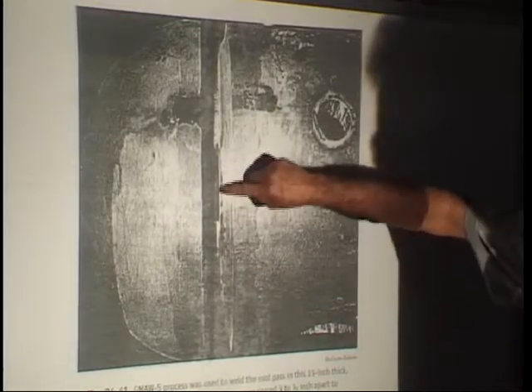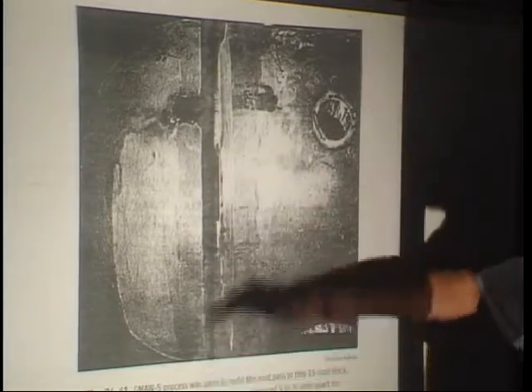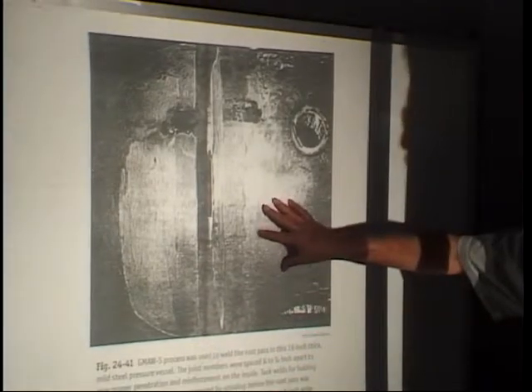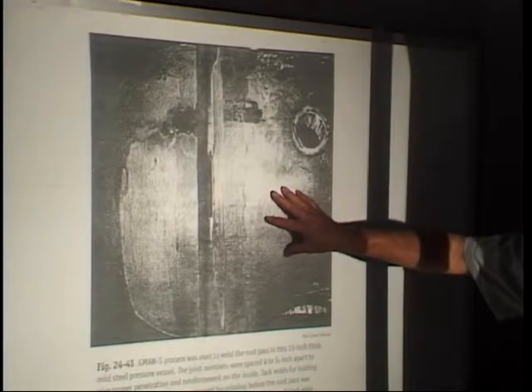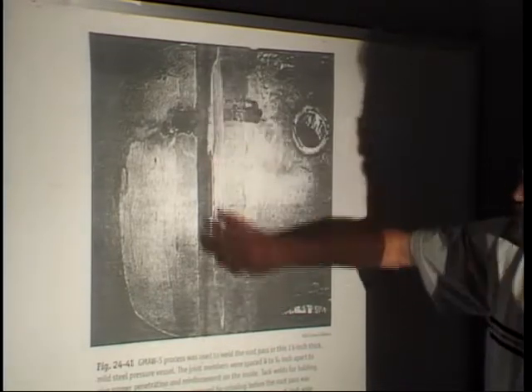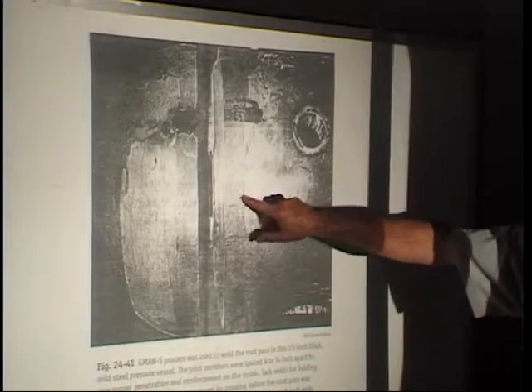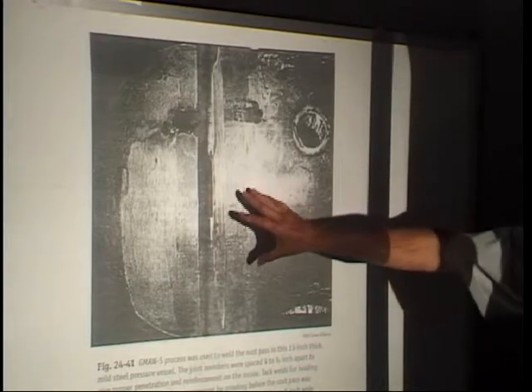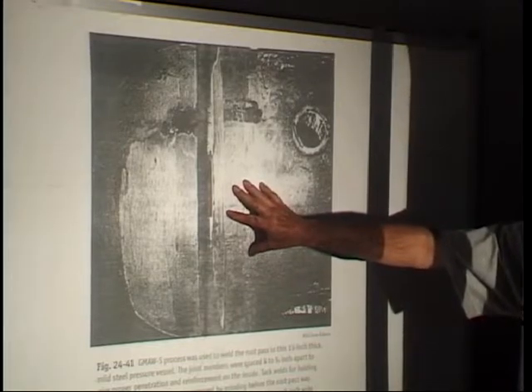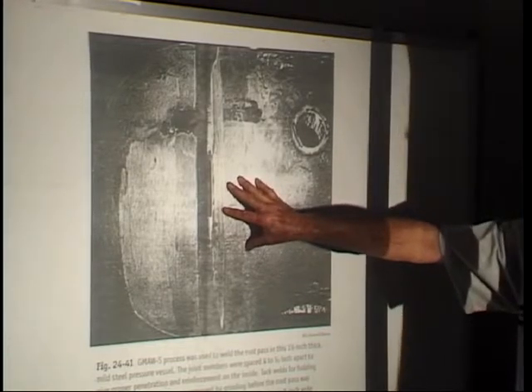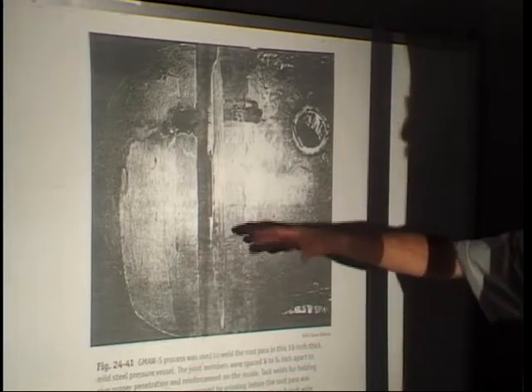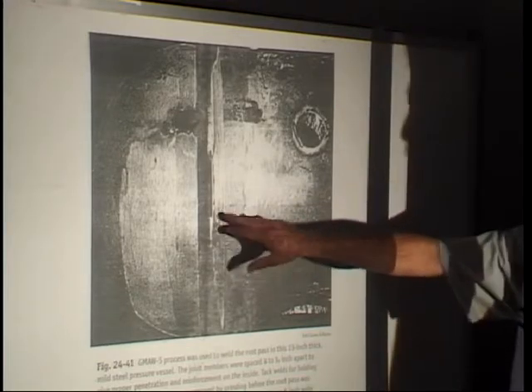Then you're going to use a high-low gauge to go into this root opening to check your alignment. Under the ASME code, you're allowed a 1/16 of an inch of misalignment. Now, on this thick stuff like that, a mismatch is really not too much of a problem because they counter-machine these, counter-bore them to match the ID, and it works pretty good. Where you come into the problem is if you're welding on like a 1/4 inch pressure vessel or a 3/8 inch thick pressure vessel. Those things have a tendency to warp, and as you're fitting them, they'll get out of round, and that makes it kind of tough, and sometimes you can get some pretty bad mismatch on that thinner stuff. This thicker stuff, however, it's pretty nice to weld.